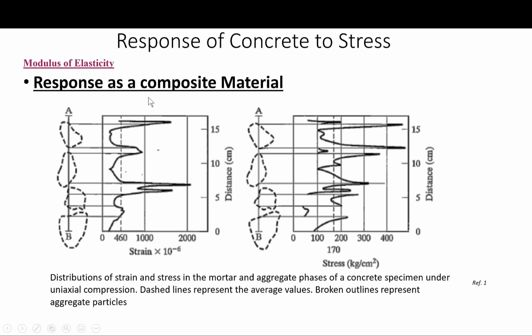We were able to measure the localized stresses and strains due to this technique, so just keep it at that. As we can see from the results of this technique, the localized strains may be as much as 4.5 times the average strains, as you can see here.